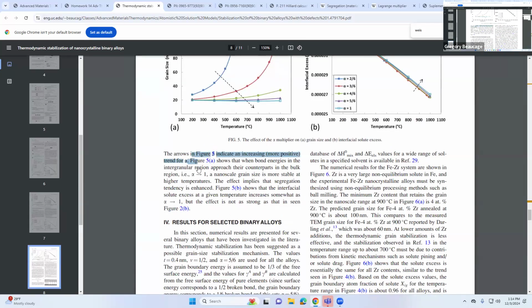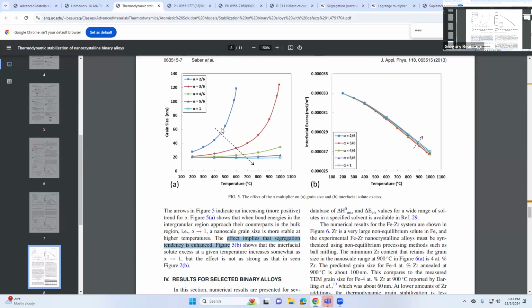The arrow in figure 5 is an increasing, more positive trend. It shows that when bond energies in the intergranular region approach their counterparts in the bulk, the nanoscale, he just says the observation that the nanoscale becomes stable implies that segregation tendency is enhanced, but he never says why. In fact, I can argue the opposite case. Maybe you look at it and see if you can figure out why. I don't have the answer to this one. This alpha thing doesn't seem to make sense to me. The definition of alpha might be important here. He isn't clear exactly what alpha means, so maybe you need to figure out what alpha means. That's kind of difficult.